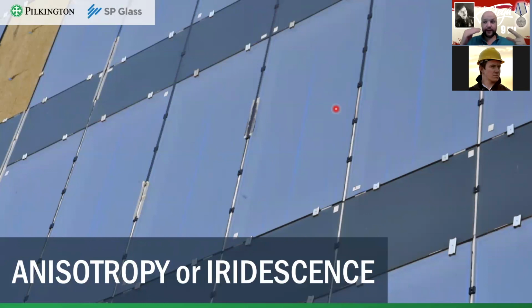The angle of light: the sharper the angle of the sun to your facade, the bigger the chance you will see it. Third is the amount of tempered glass you are using for your IG unit. In this regard, if as an outside glass you have a laminated glass of 2 tempered glasses laminated with each other, that greatly increases your possible anisotropy effect.